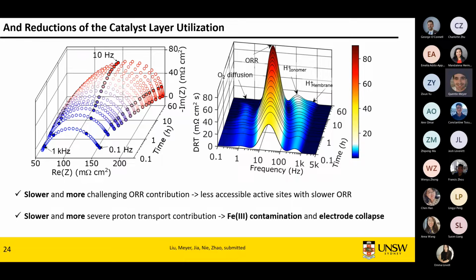So now this was all pretty good, but the problem you've got when you capture polarization curves, or even when you do CVs, is your device is not at the current you're degrading it at. So we went to doing impedance measurement at 1 amp per centimeter square, and that corresponds exactly to the state of the cell as the voltage is dropping. So initially, you have basically a bit of charge transfer, proton transport, and then a little bit of mass transport here. And then you can see the Nyquist gets really, really big.